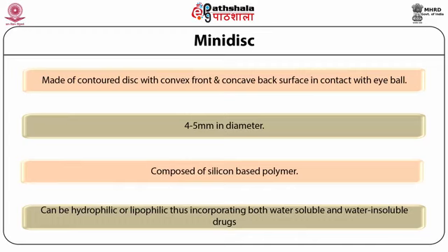Sulfisoxazole, a lipophilic drug, when incorporated in a hydrophilic matrix, showed drug release for up to 170 hours. However, gentamicin, when incorporated in a hydrophobic matrix, showed a release for 320 hours.